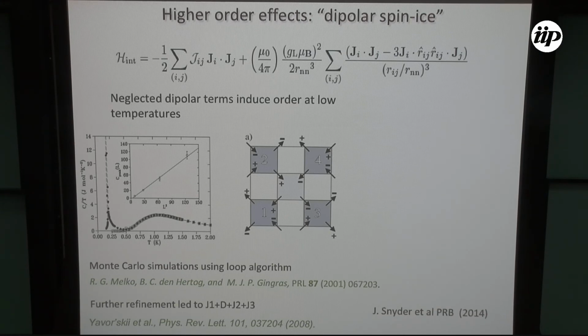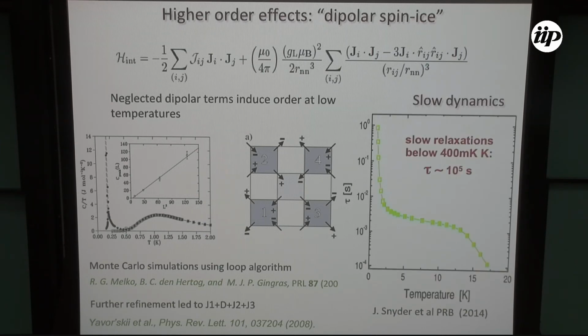There's some work we did together with Gerardo, Daniel, and Flavia, and Diego Rosales, who is not here, where we also tried to go a bit further by looking not only at the zero field experiment, but at higher field experiments. And we saw that not only third nearest neighbors were important, but you had two kinds of third nearest neighbors, and it was important that those two were slightly different to explain the results. And we think that that is probably coming from small lattice distortion. So as I said, even in a system that you think is perfectly frustrated, if you refine your analysis enough, you'll find that there's some evidence of something that's not perfectly what you think it is. Okay, so going back to this, why wasn't any kind of peak seen there?